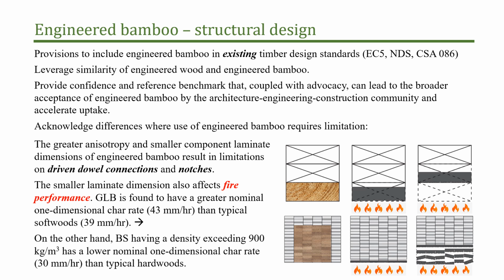The key is to acknowledge the differences where the use of engineered bamboo requires limitation. So bamboo is highly anisotropic, much more so than timber, and also the components that we're using are much smaller. The laminates are on the order of 5, 6, 7 millimeters thick, rather than, let's say, a standard 2x, which might be about 38, 40 millimeters thick. So we do have some limitations associated with this. The high degree of anisotropy, hard word to say, I apologize, means that we have some significant limitations on dowel type connections, driven connections. You cannot nail into engineered bamboo. It just doesn't work. And also notch factors and notching.